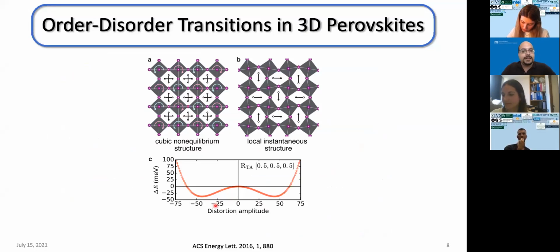Currently, how we understand it is that the atoms in methyl ammonium lead iodide fill a double well potential, as you see here in the bottom, where the x-axis is an amplitude of an octahedral rotation, and the y-axis is energy. Now, at low temperatures, the atoms are confined to the bottom of the wells, meaning that they rotate in small amplitudes around a finite octahedral rotation. And the structure that we have is some low symmetry structure, in this case, a tetragonal structure.